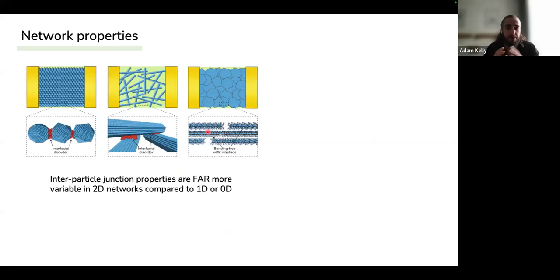So one thing that we find with two-dimensional materials is that the interparticle junction properties are much more variable in these ones than they are in 1D carbon nanotube networks or 0D metal oxide networks, for example. So the overlap area between two 0D particles, it doesn't really matter how you orient the particles. The junction overlap is going to be basically the same. And it's quite similar then with 1D particles too. I mean, you can twist them a bit, but people have been trying for 20, 30 years to do alignment on these, and it's quite difficult.